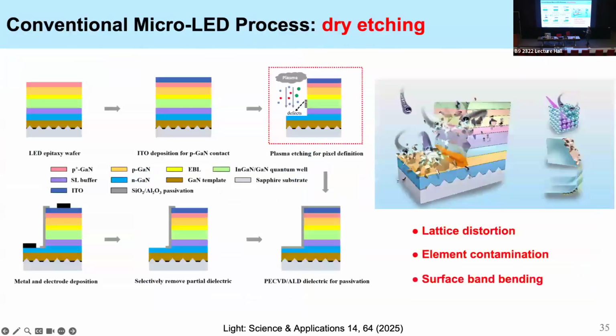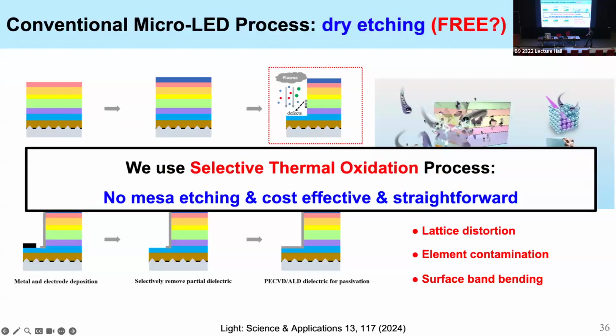So why is that? The reason is that in a normal micro LED fabrication process, people have to use an invasive and destructive process called dry etching. Basically, in dry etching, you use high-energy plasma to bombard the surface of the LED wafer to remove material and define the pixels. When you do that for a large LED, it's not a problem because most of the active area is far away from the sidewall. But for the micro LED, the active area is very close to the sidewall, and electrons and holes can easily diffuse to the sidewall. The sidewall creates a lot of problems because it has lattice distortion, element contamination, and surface band bending. That traps electrons and holes into phonons instead of photons. So the question is, is it possible to develop a technology that does not use dry etching?